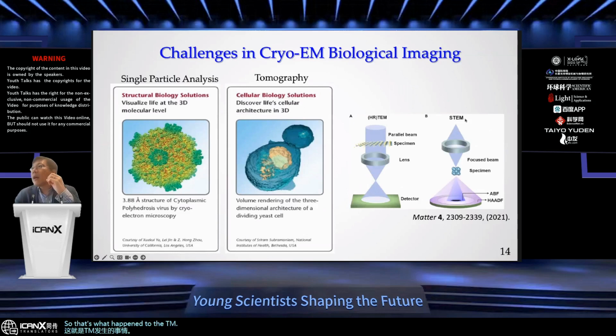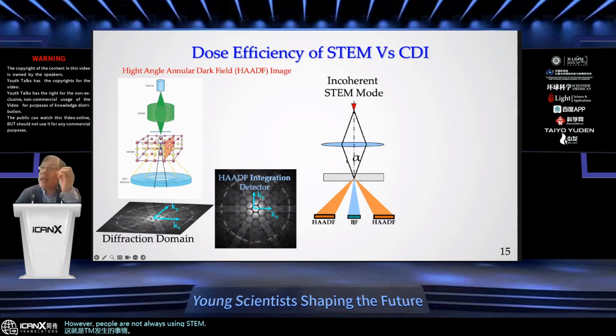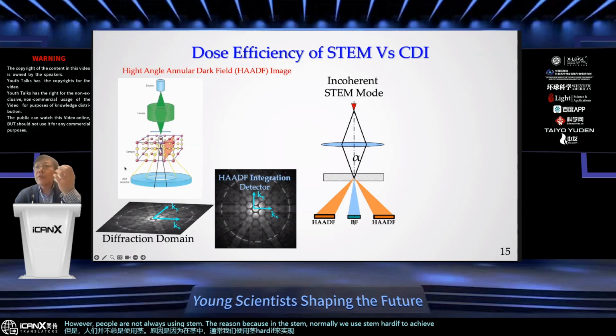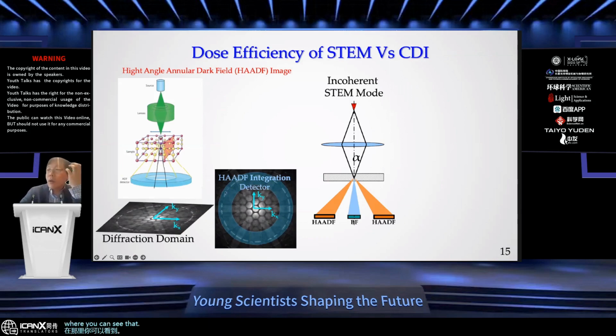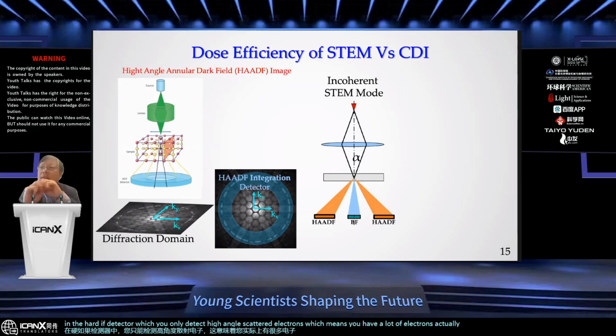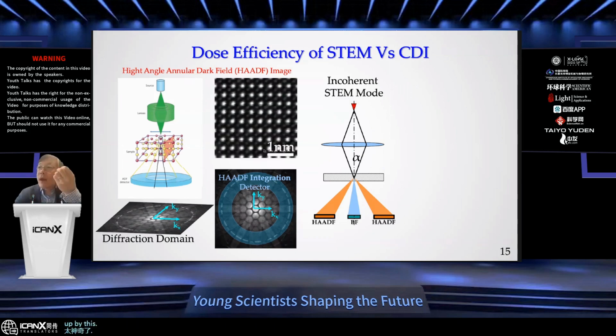However, people are not always using STEM. The reason is that in STEM, normally we use STEM HAADF to achieve high resolution. If you use the HAADF detector, as you can see, this is the HAADF detector geometry, where you only detect high-angle scattered electrons, which means you have a lot of electrons actually missed by this detector. Okay, although you can achieve really high resolution, you miss a lot of electrons.